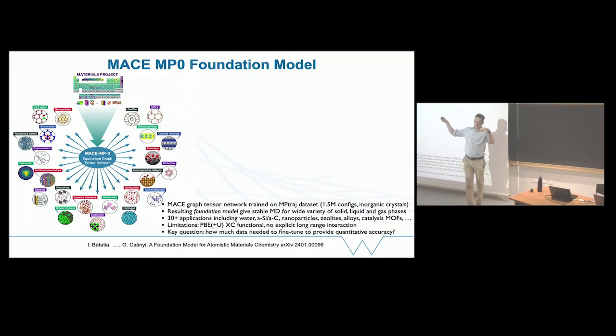You do 2 hops, essentially, where you pass information from a site to its neighbor and then to the neighbor of the neighbor. So rather than having an effective cutoff of 6 or 7 angstrom, you have a cutoff of 12 or 13 angstrom. And that, it turns out, is just about enough that it works okay for systems in which there's a bit of charge transfer or a bit of long-range electrostatics. It works surprisingly well, given that there is no direct treatment of the Coulomb interaction. It's really just the same ideas that we've seen now, but a bit longer range.